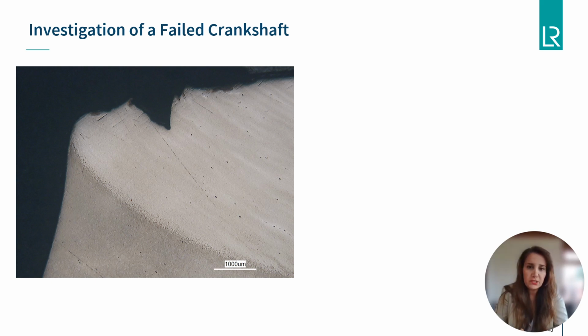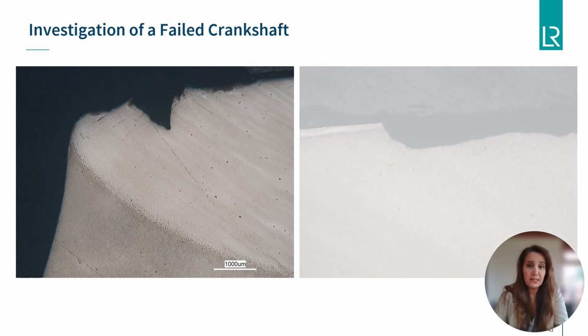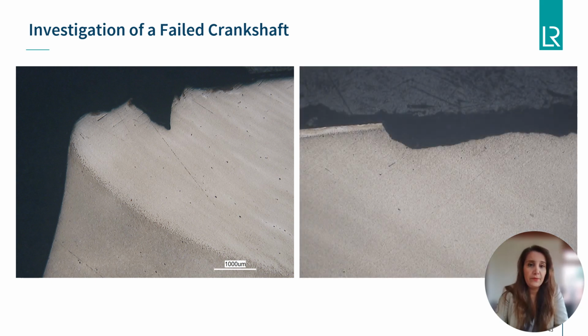The final sections revealed evidence of a hardened layer at the external surface of the main bearing journal. It was evident that the fracture initiation area was adjacent to the extremity of this induction hardened layer. I have to note that the depth of the hardened layer was found to be consistent with that specified for this component.